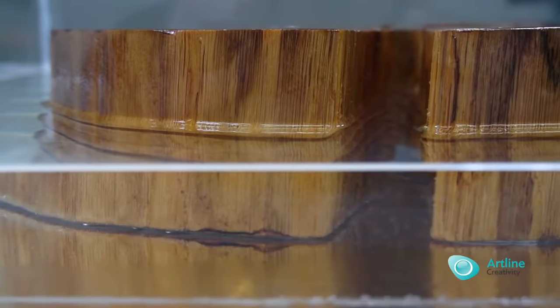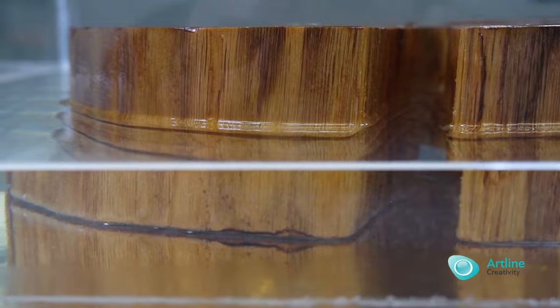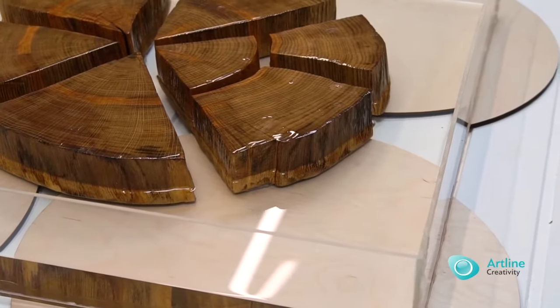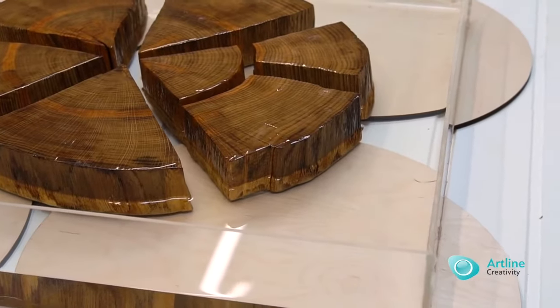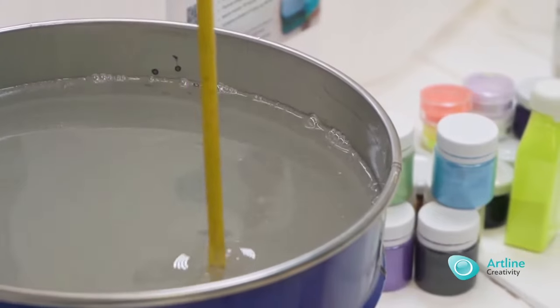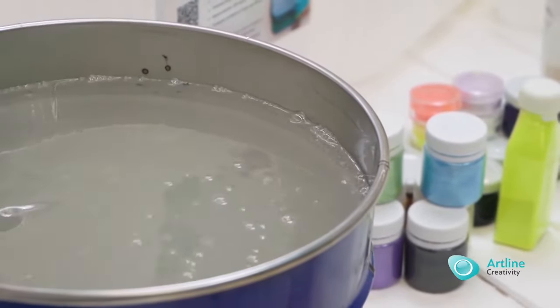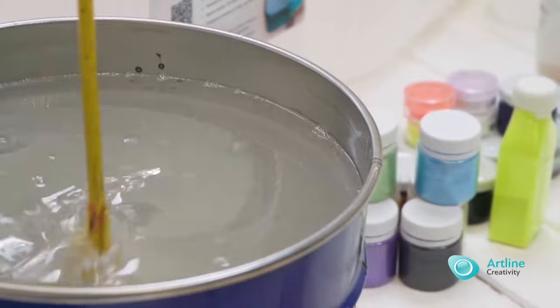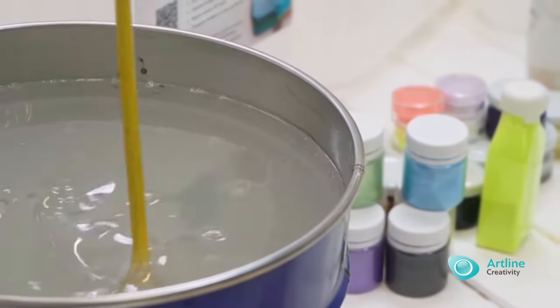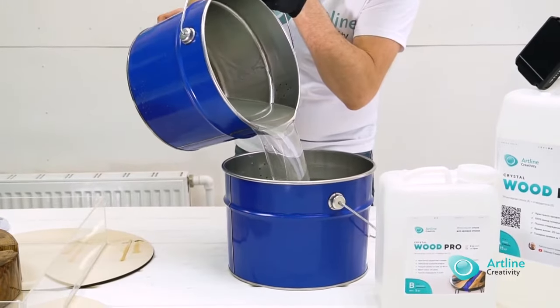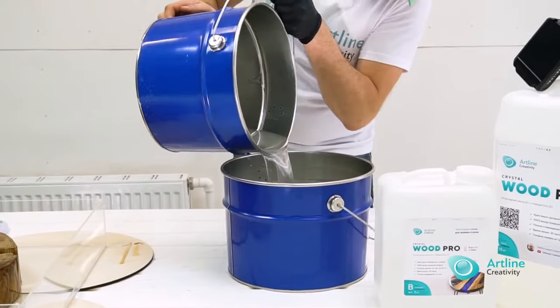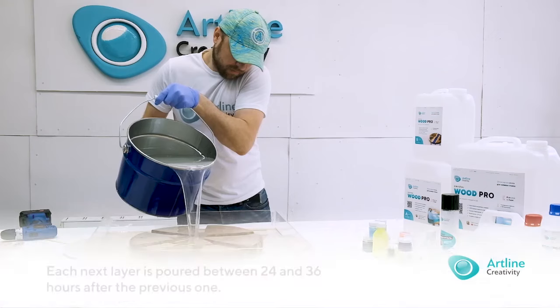For the first 30 hours, the resin remains liquid, which allows air bubbles to come out on their own. Then starts the process of temperature release and solidification. At this stage, it is necessary to fight the bubbles that have formed on the walls of the formwork and casting object. If a new layer is poured earlier than it should be, the lower layer will boil because there is nowhere to release heat.